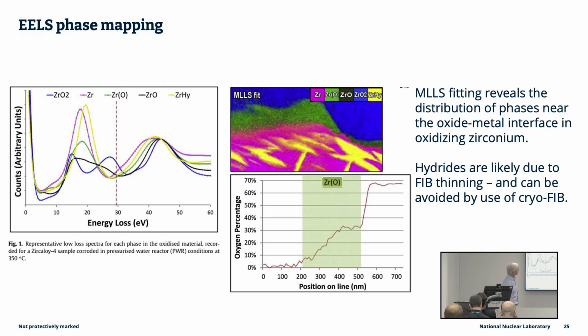This is a rather more detailed piece of work, similar to the image I showed at the beginning. So we've got here the characteristic shapes of the plasmons for the phases which are present around the interface of some oxidized zirconium. As I said at the beginning, the hydrides are present in this image and really quite distinctive, but are mostly artifact due to the FIB preparation. The other interesting feature is that this technique is probably the best there is for really showing quite clearly the suboxide phase, which is present at the oxide metal interface. And it was also possible to extract the oxygen concentration profile as you come in from the oxide through the suboxide and then through a decaying diffusion profile of oxygen into the metal.